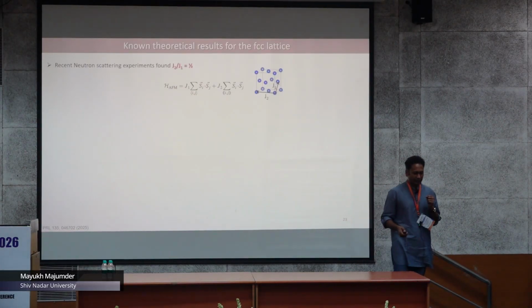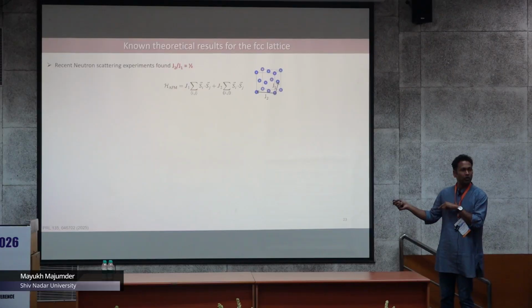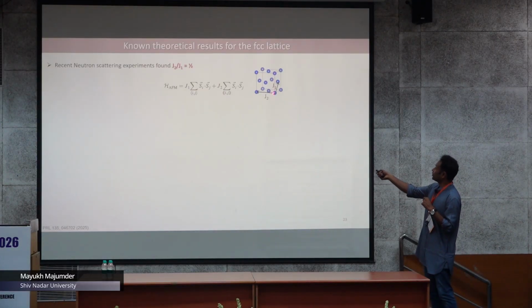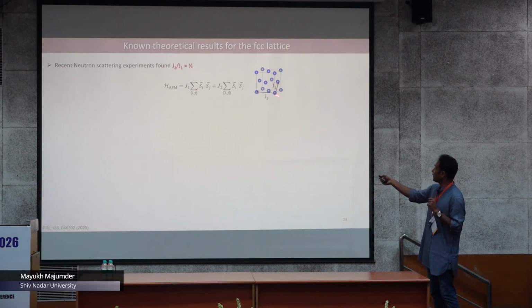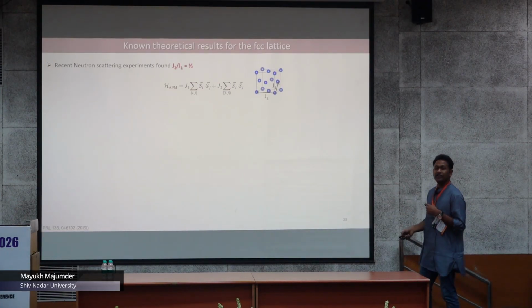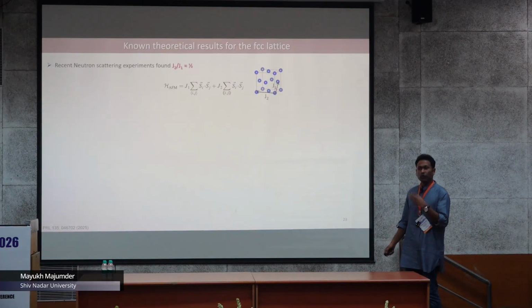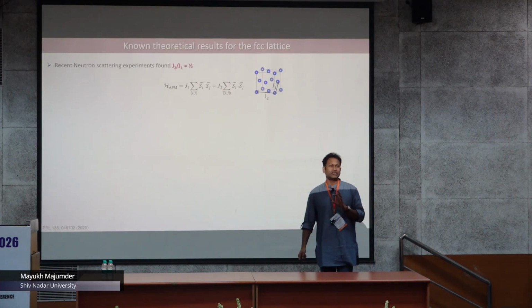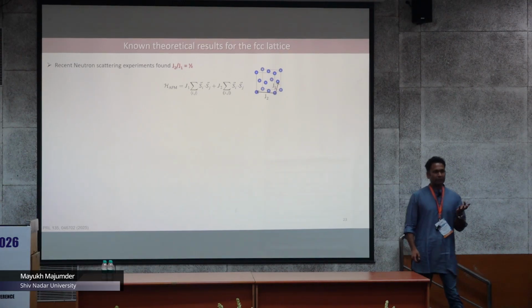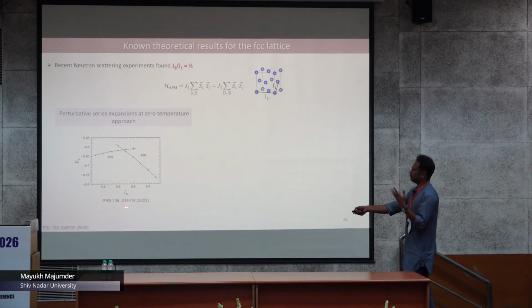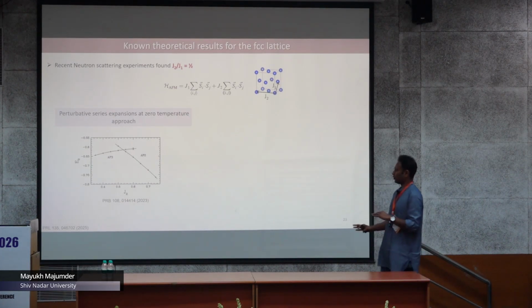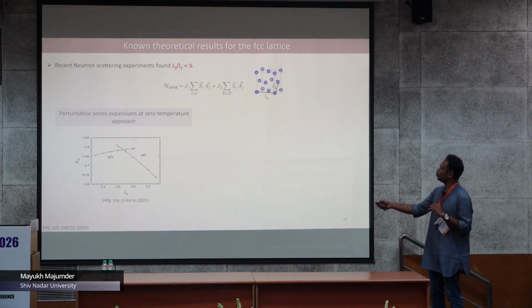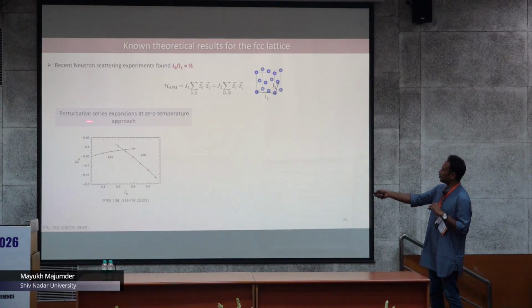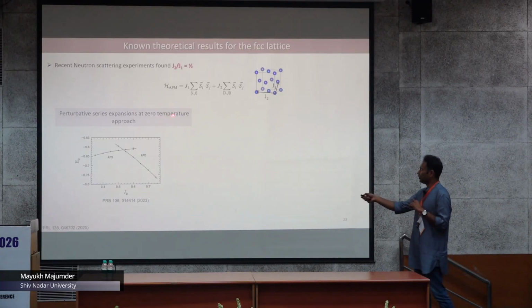Okay, so now I should mention that one recent neutron scattering experiment shows that for this particular compound on which we worked, if you consider J1, which is the nearest neighbor interaction, and J2, which is the next nearest neighbor interaction, they have found out that the ratio of J2 by J1 is half. So we look for those theoretical results where they have considered this J1, J2 model in the case of the FCC lattice. We are not going to show all the results, but these two results that I'm going to show. So people have done this kind of approach, like a perturbative series expansion at zero temperature approach.